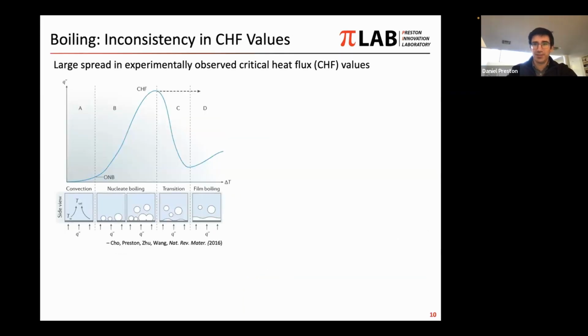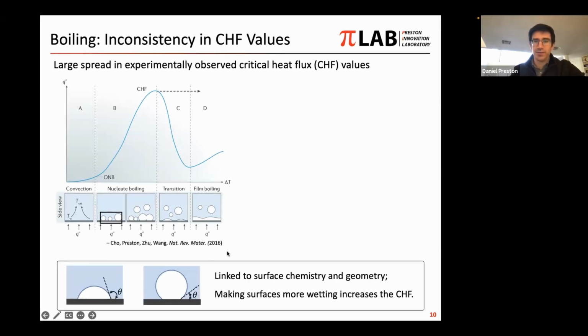So with condensation, it seems like we're actually getting an advantage from this contamination on the surfaces, resulting in dropwise mode and improving heat transfer. But for boiling, it's a different story. So boiling, if we're getting contamination on the surface, first of all, it usually ends up reducing our heat transfer performance. And second of all, providing a lot of inconsistency in experimentally reported values. And so we think about the critical heat flux, for example, definitely linked to things like the surface chemistry and the geometry of the surface, things that you want to control very carefully for some of these surfaces with engineered wettability, and things that you want to make sure that you also keep consistent when you're trying to do fundamental studies of CHF on maybe metals, different types of structures.